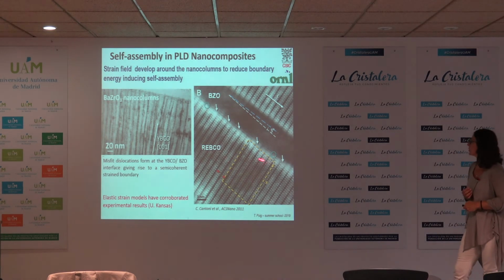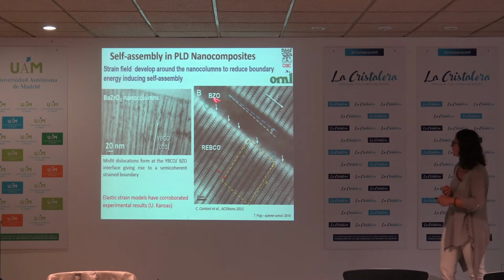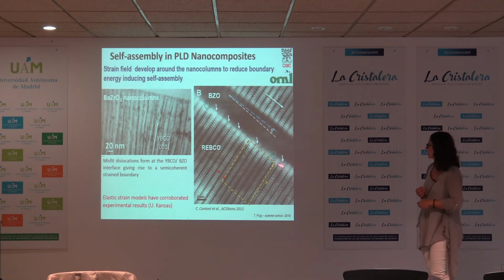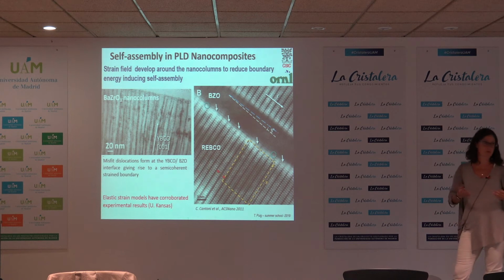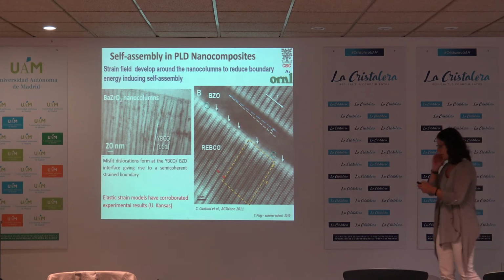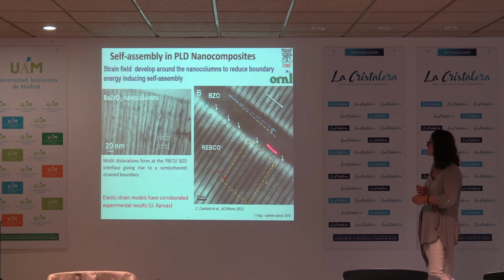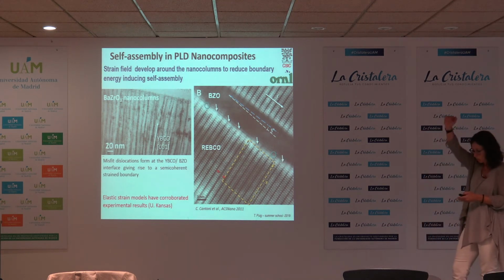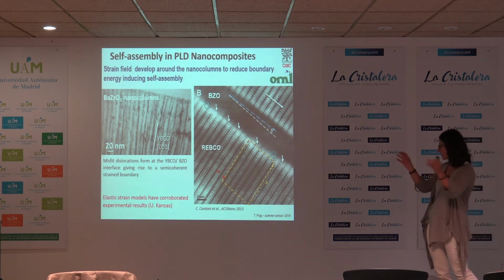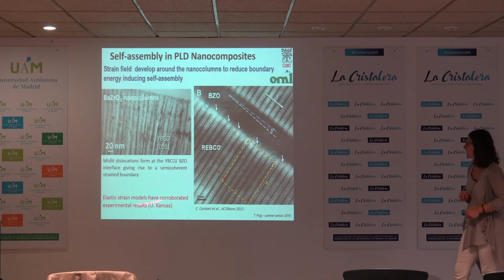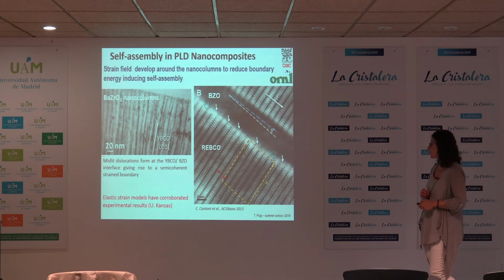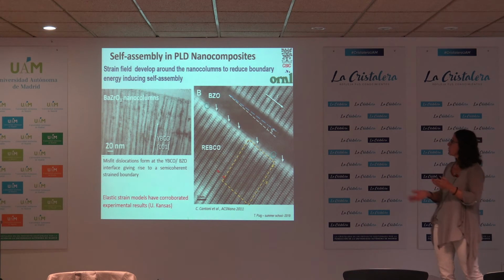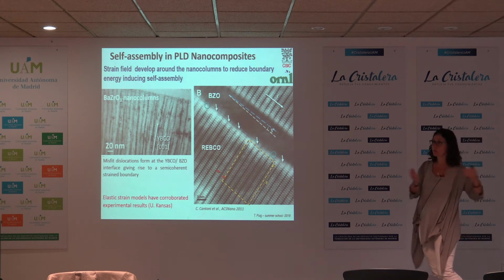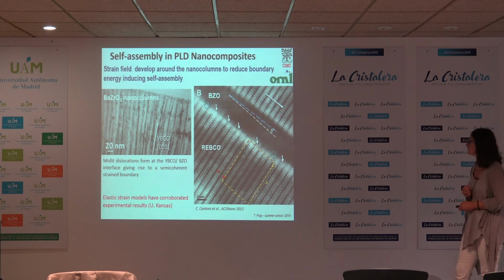There has also been a lot of effort in understanding the strain between the rod and the YBCO matrix, and realizing how much this semi-coherent interface also plays a role as pinning centers. In fact, this strain is what at the end allows orienting all these nanoparticles in the form of a rod, instead of having them all distributed. And there have been elastic models able to corroborate the experiments, which can also determine the phase and the size of the nanorod that will be formed, depending on what material you are using.